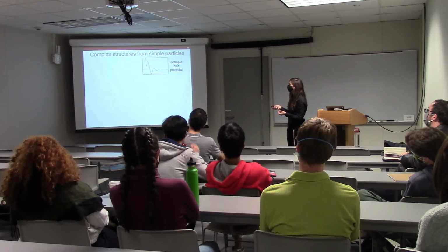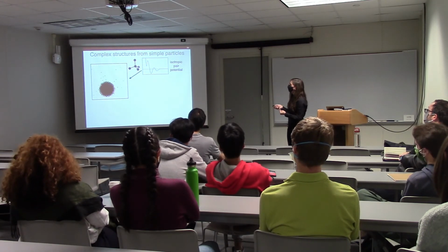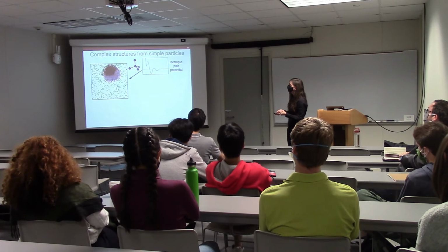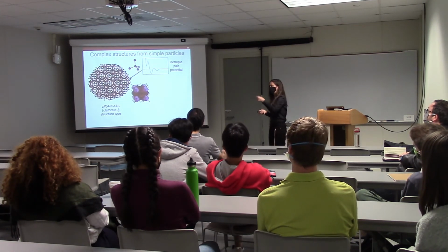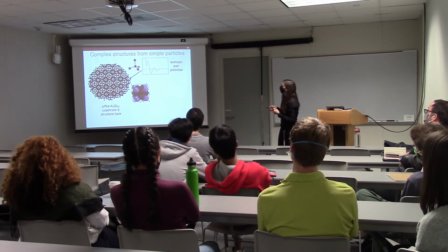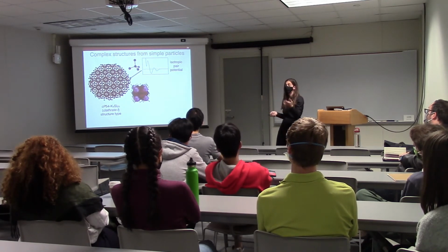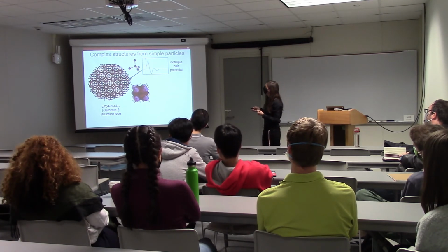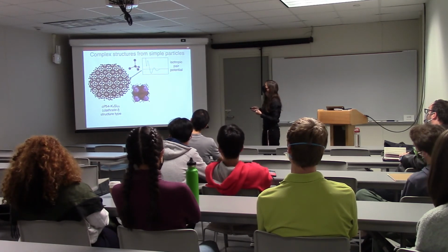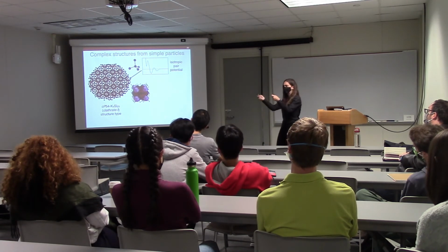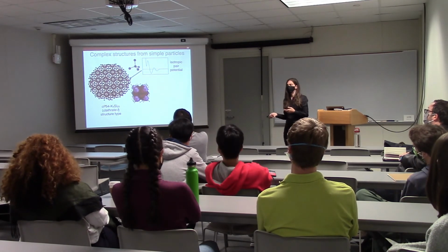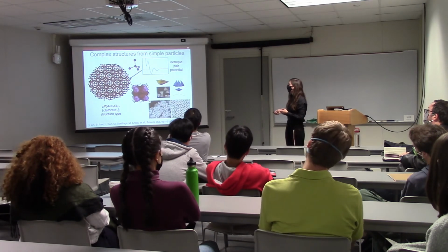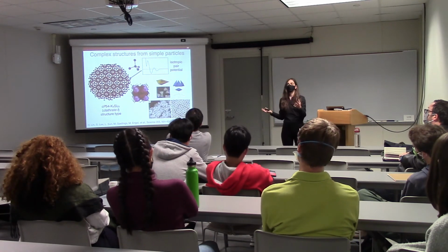So we're taking our isotropic pair potential. This one forms this tetrahedral local environment that assembles into the clathrate crystal structure, which actually, when it comes to the wells and how they align with the neighbors, we'll actually see that all of the low coordinated structures with, for example, 4 nearest neighbors will have this minimum that is not net attractive. And then the second nearest neighbor shell is the one where the attractive minimum sits. Okay, so this is one of the structures that assembles, and we know that it is also observed in nanoparticles.